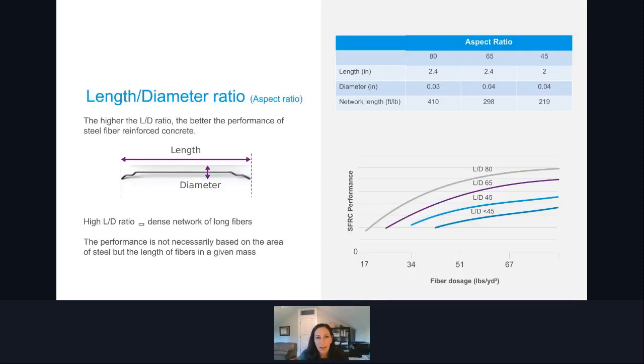Generally speaking, the aspect ratio is important because higher aspect ratios tend to perform better, just in a generalized way. And the reason for this is because with a higher aspect ratio, you can expect to have a dense network of long fibers, because it really does come down to the network length of reinforcing. I've seen other claims of the fiber count being most important, the number of fibers, but for reasons that we'll cover in just a moment, I tend to disagree with that, because it's really the total network length.